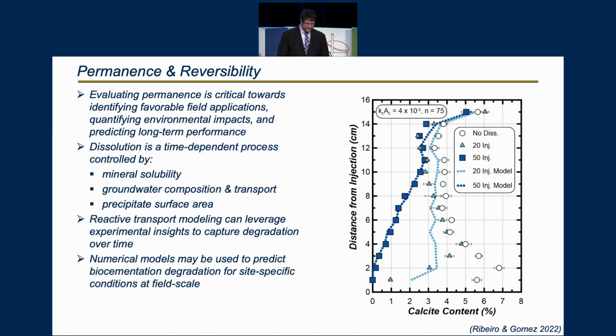Reactive transport modeling can leverage some of these experimental insights in order to be able to capture degradation both spatially and temporally. As shown here, a series of soil columns were treated identically and then exposed to 50 dissolution acidic injections, which were applied from the bottom upwards. The data points shown are actually measured from physical soil column experiments and demonstrate calcite contents as a function of distance from the injection source. And the dashed lines shown are PHREEQC 1D reactive transport model simulations, which can reasonably capture such trends using existing mineral dissolution frameworks. Of course, these models show great potential and ultimately may be used in the future to help us predict biocementation degradation for site-specific conditions when the technology is ultimately applied at field scale.